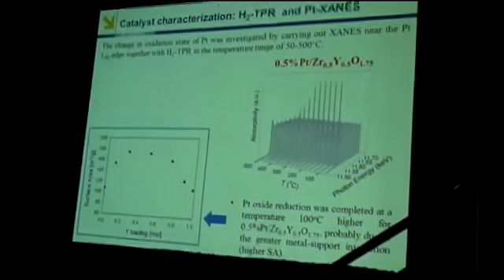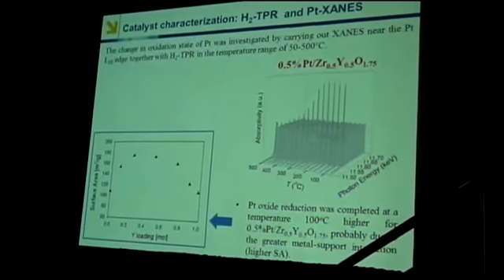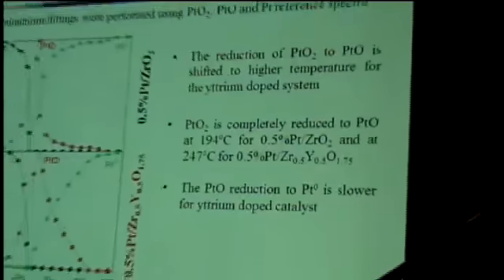When we go to the higher surface area material, 50% doping level, it takes a slightly higher temperature to achieve the complete reduction of the platinum oxide to the metal. And you can see this, again, there's a difference in the surface area there. So that's probably due to metal support interaction.